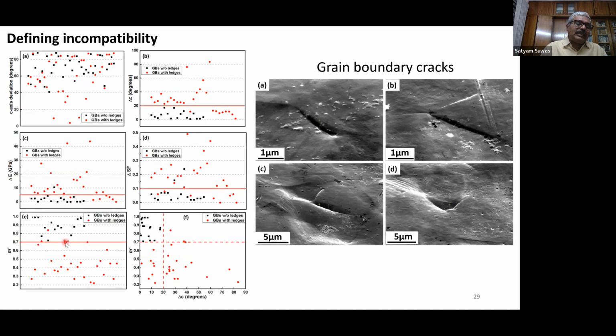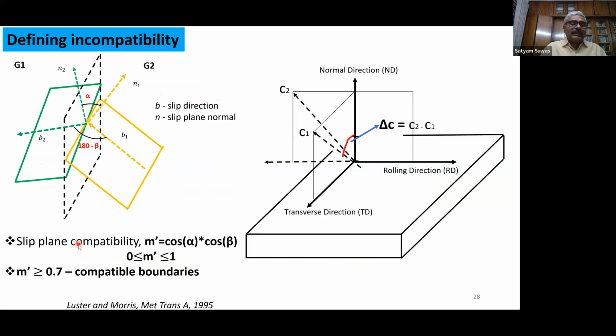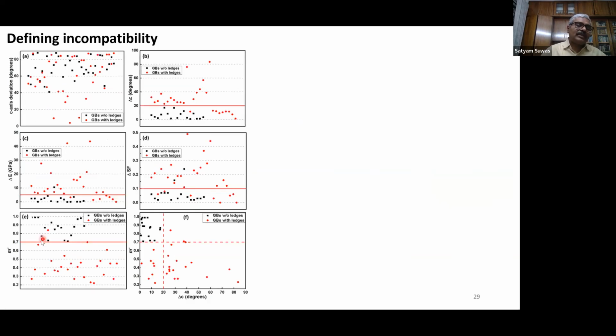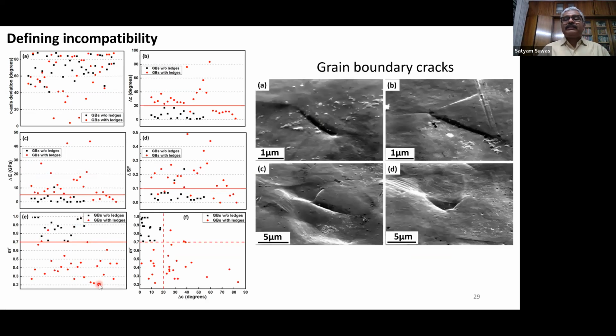Similarly, the m prime factor is also lower for the case of grain boundaries with ledges compared to those without. If we go back, we could see that if it is higher than 0.7, then it is a compatible boundary. So 0.7 is the criterion here, and in this case it is compatible, and in this case it is not compatible. So this is also fitting very well with our concepts of ledges and all that.